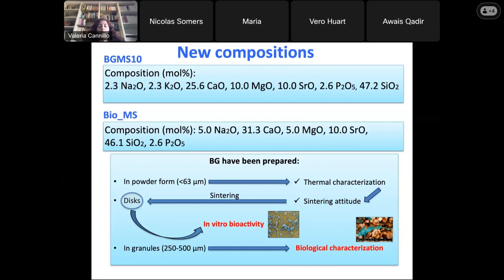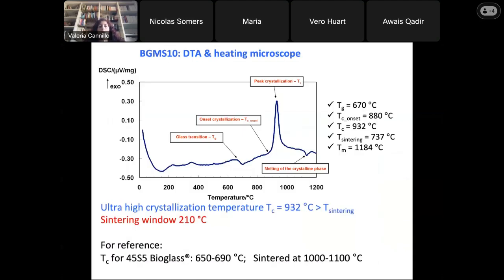And then they have also been produced as granules in the range 250-500 microns for the complete biological characterization, and as I will illustrate in the following, also for in vivo implants. So here you have the characteristic temperatures of the bioglass, and as you can see, you have an extraordinarily high crystallization peak, which is about 932 degrees, which is one of the highest ever reported in the literature.